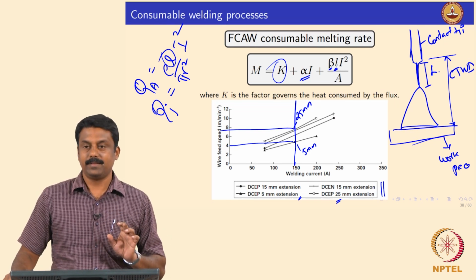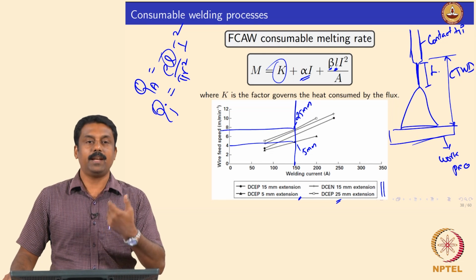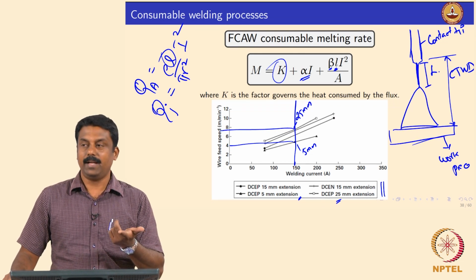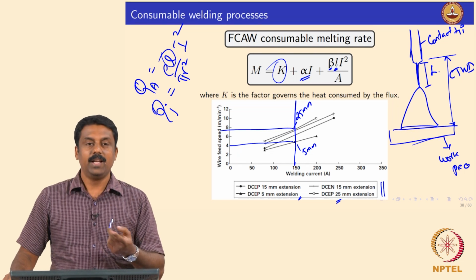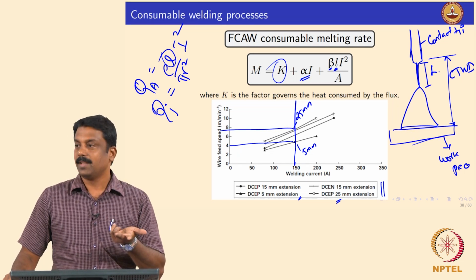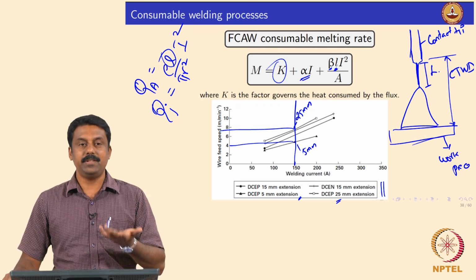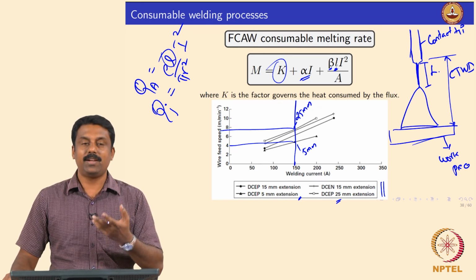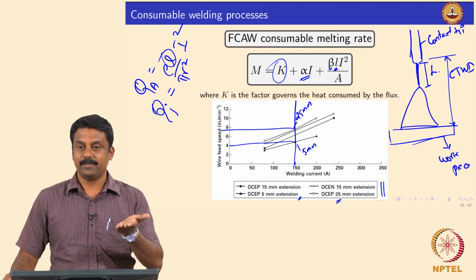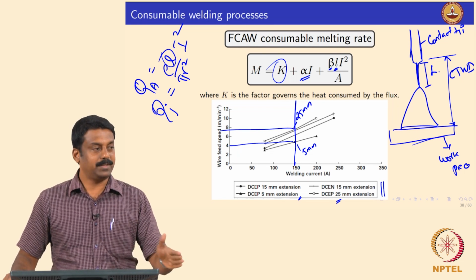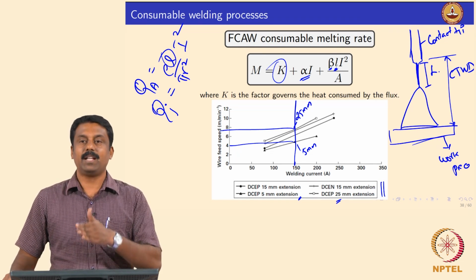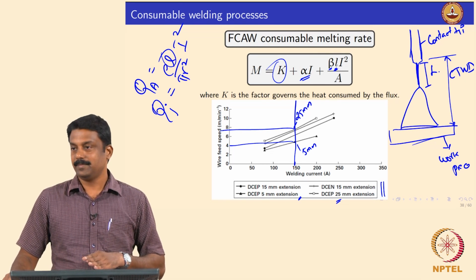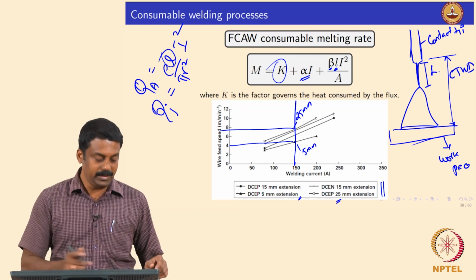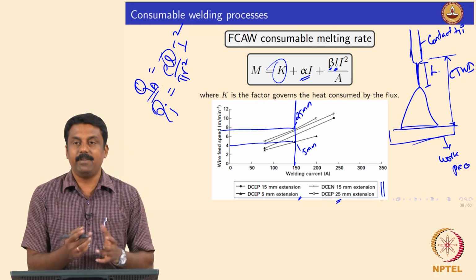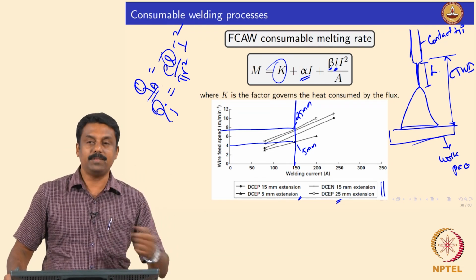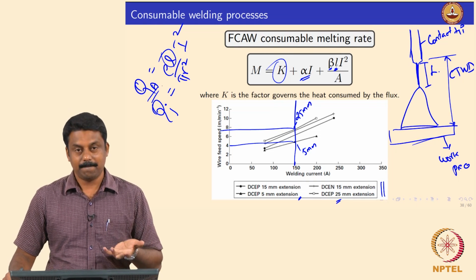So, composition is fixed. If composition is changing, latent heat of melting is changing, right, and then H is changing, and then you also change Cp, specific heat capacity. When Cp changes, then you also change the heat required to increase the temperature of the droplet. So, now you fix the process, you fix the chemistry, and what are the parameters you can contribute. So, in this QA term, the only parameter which is changed irrespective of process and the composition is current.